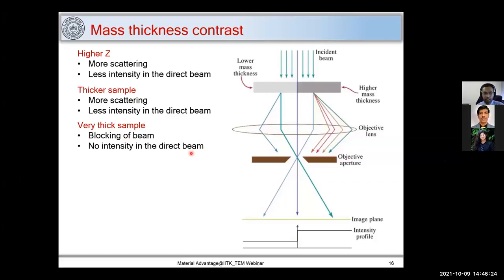That is why our sample thickness, when we prepare samples for TEM, is around 100 to 150 nanometers, so that the beam should not get blocked.